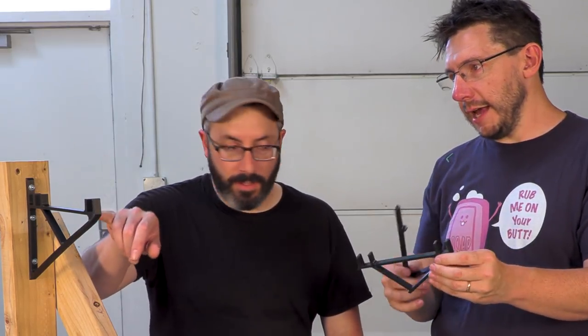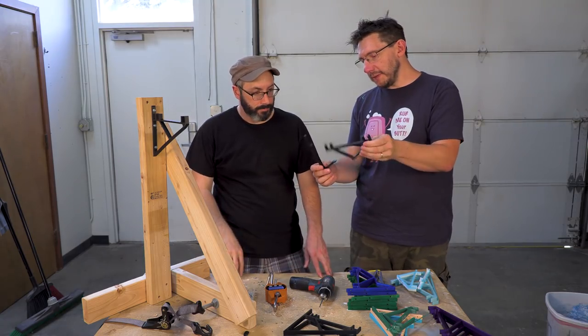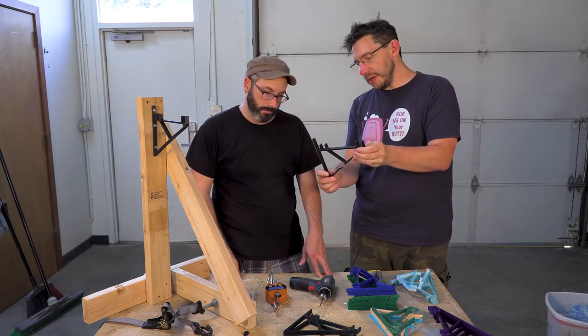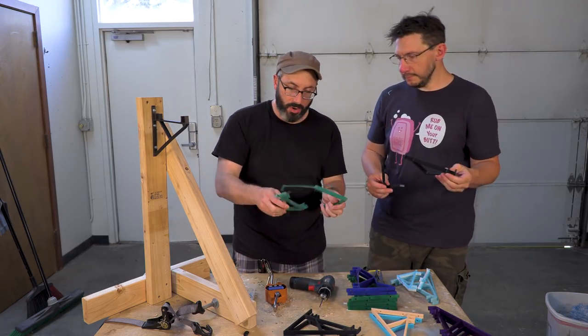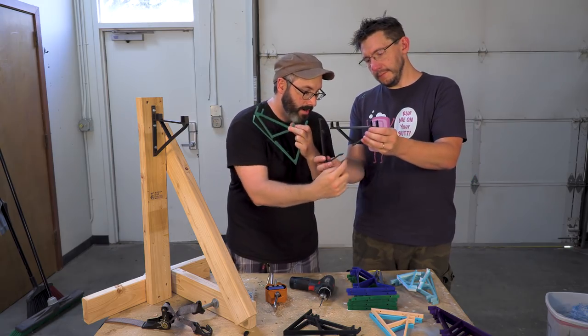There was no damage here, the Nylon X. Yeah, it's interesting. This is the only one that did that. It didn't seem like this flexed much. It seemed like there was enough force to where the compression here caused it to break away right up top. And I think all of... let's just double check, but all the ones that broke along this piece. Yeah. Look at that, right there. Same thing right there. Yep.